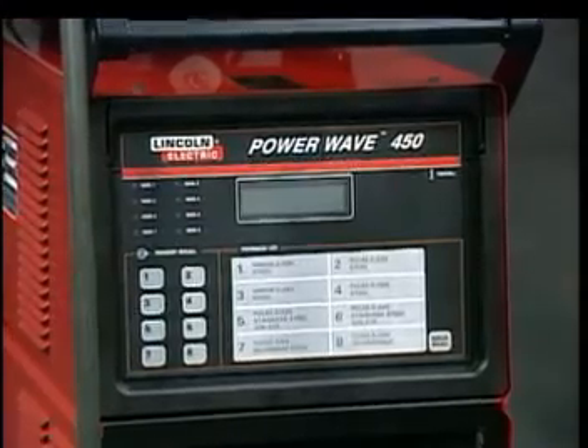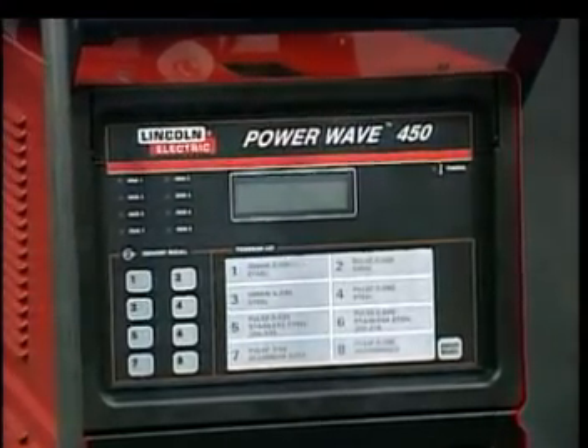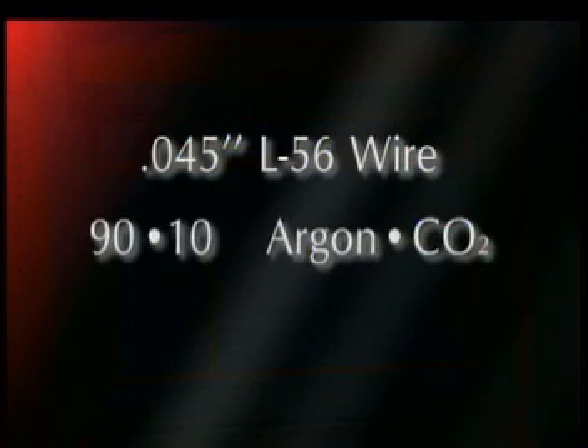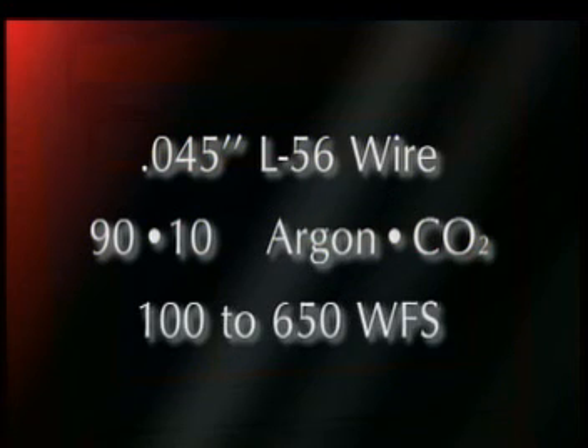We took a Power Wave synergic power source and loaded it with .045 L56 wire and used a 90-10 argon CO2 blend. We started at 100 inches per minute wire feed speed and increased the procedure to 650 inches per minute. The synergic property of the Power Wave sets the correct arc length for each wire feed speed. The CV mode is first. Note the definite transitions between the short-circuiting, the globular, and spray arc transfer ranges.